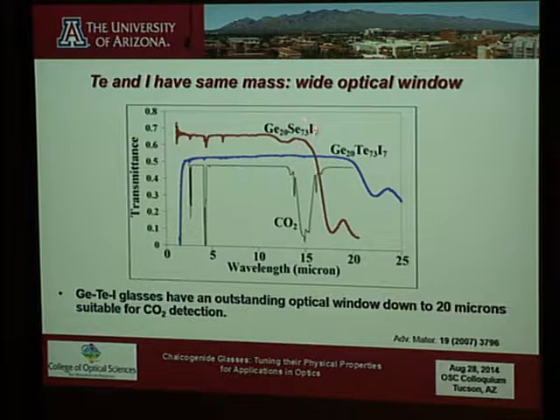So it's very complicated to actually control the stoichiometry with high accuracy because you're always losing some of this iodine. So in practice, it's a very difficult glass to actually produce in high optical quality. And the second thing, which is even more problematic, is that we found many years after making it that the iodine has a tendency to also just get out of the structure. After 3 or 4 years, you find out that the surface of the glass is degrading, and it's degrading again because the iodine is coming out.